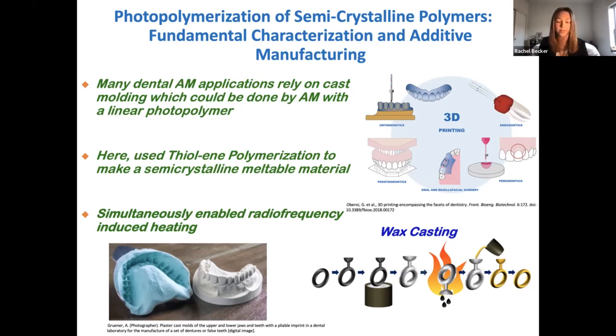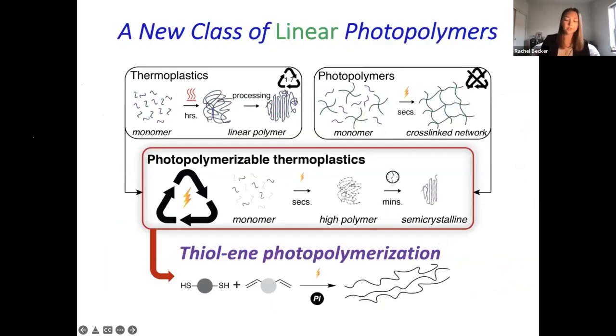These material properties hold great potential in cast molding dental devices, similar to the wax casting process shown on the bottom right corner of the screen. The biggest advantage of this material is we're now able to have a 3D printable wax material, which can be locally heated to remove the mold. So the material used in this project is based on the thiol-ene click reaction. This mechanism rapidly forms a semi-crystalline, high molecular weight polymer. These linear polymers are recyclable by reheating and applicable to 3D printing due to the fast polymerization and crystallization kinetics.